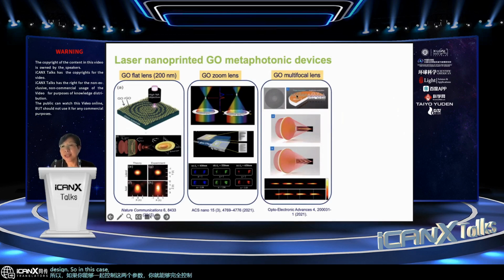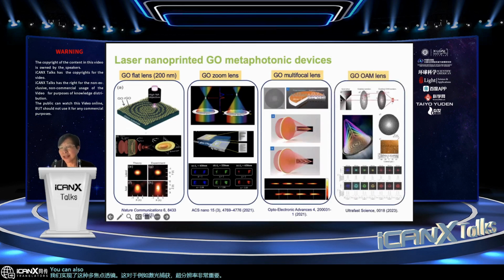So in this case, we can encode the different wavefronts we want to achieve. For example, we achieved this kind of multifocal lens. This is quite important for laser trapping and for super resolution imaging. You can also encode a spiral phase and combine that with the focusing phase. So in that case, you have quite a complex phase, but the fabrication is just in one go. Basically, one fabrication can give you multiple phases.